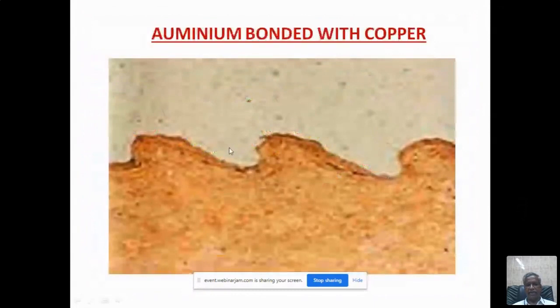In all the good explosive welding bonds, you will find this type of wavy interface at the interface. So like this is an actual micrograph. This is aluminum alloy. This is the copper alloy. So you will get this type of wavy interface. From this point to this point is called the wavelength, and this is the amplitude of this wave. So the amplitude of the wave will decide the bonding strength. If the amplitude is higher, then the bonding strength will be larger.